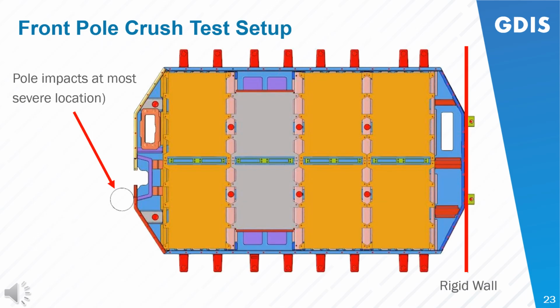This plan view basically shows a layout of the test. You've got a rigid wall, which is actually the support at the rear end of the structure, and then the pole is actually applied in the front in the most severe location. In this case, the pole is displaced a little bit inboard from the fore-aft member to make sure that it's the most severe location for the test.